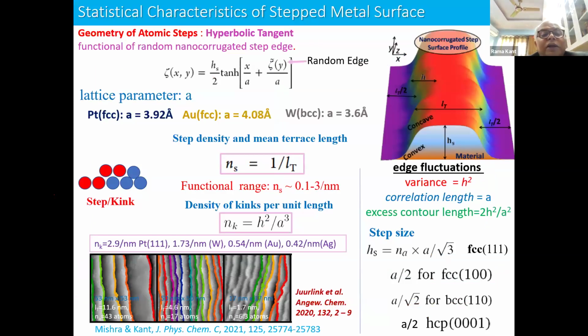So here we model a step as a tan hyperbolic function with a fluctuating term, xi tilde of y or something. So this is where we model it. And then there is a kind of periodicity in it because of the hyperbolic function, you can repeat things. And then the height of my step is hs, and a is my lattice parameter, and this is my edge fluctuation in that.